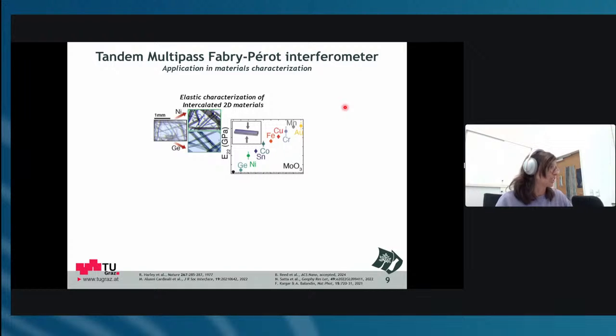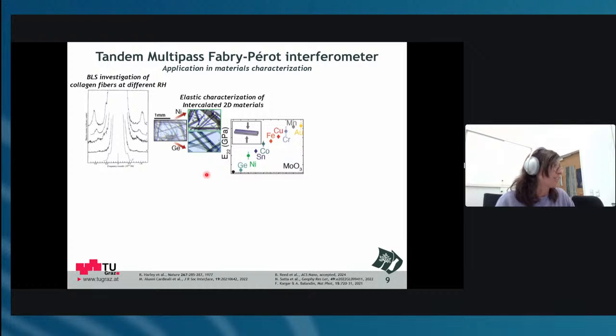Yes, and here maybe some applications in materials characterization that have been done with this sort of device. So, for example, this is what my supervisor in the US is doing, Professor Koski. She's doing a lot of intercalation of 2D materials and looking at the elastic properties, how they develop when you put different intercalates into 2D materials. In the 70s already, collagen fibers were measured at different relative humidities. They went a little bit high with the laser powers. That is a little bit of an issue, but it's nice that you really saw how the humidity affects the frequency shift of the collagen fibers.